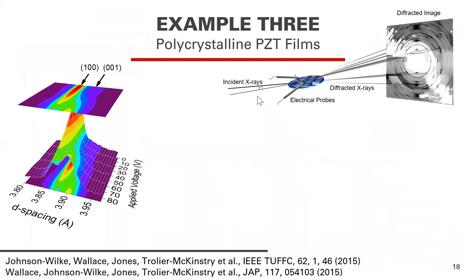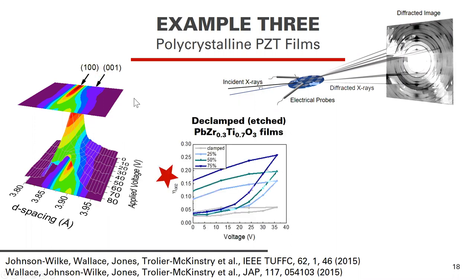We've been collaborating for several years with the Susan Trolier-McKinstry group at Penn State under an NSF collaborative project. And we deployed these techniques on thin film PZT. And so here you can see a schematic representing a small incident angle on an electrode and a diffraction pattern shown up here. As we apply voltage to the sample, you can see representative intensity interchanges between the 100 and the 001 peak. Now, we studied a variety of different samples.